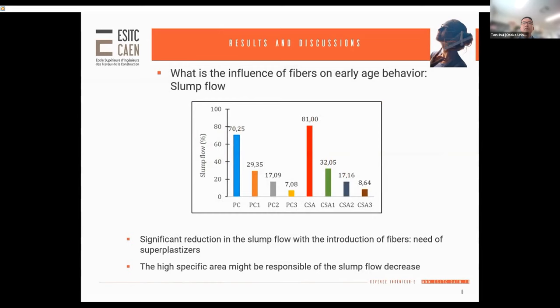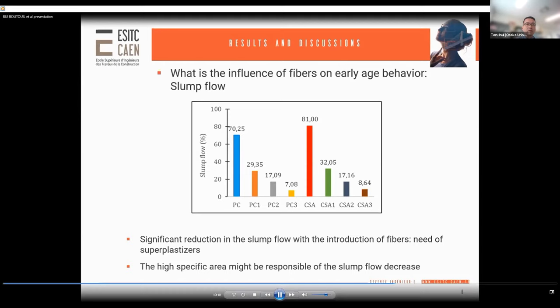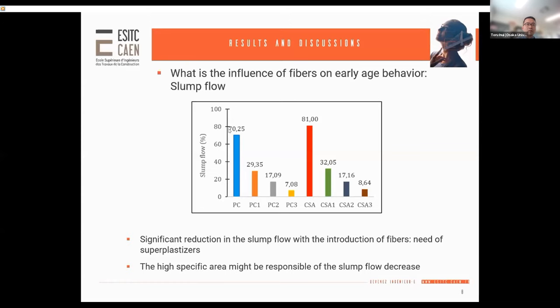This influence can be seen first from the slump flow results. As you can see from this figure, the evolution of slump flow of samples at the fresh state shows a significant reduction in the slump flow with the introduction of fibers. This is why we need to use some plasticizer when using this kind of fiber. And from previous results, we have demonstrated that probably the high specific area of the fibers might be responsible for the slump flow decrease.